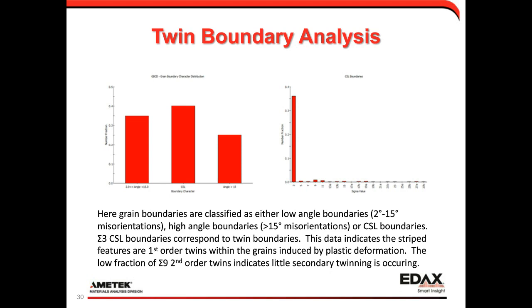We can see that there's a pretty high fraction of CSL boundaries present in the material. It makes sense. It's a TWIP steel with lots of twins. We'd expect lots of CSL boundaries. We can also classify those as different types of CSL. So we see there are primarily sigma-3 boundaries, but there are a few second-order sigma-9 boundaries in the distribution as well.